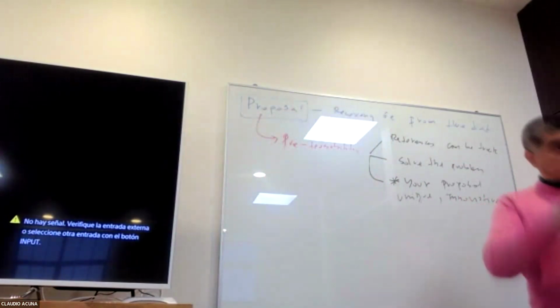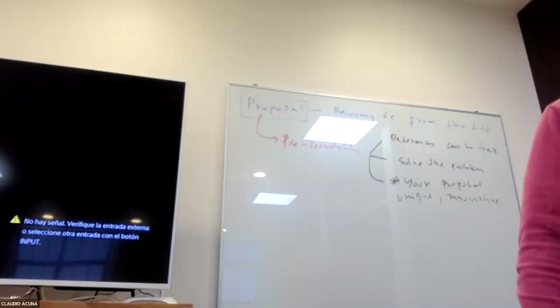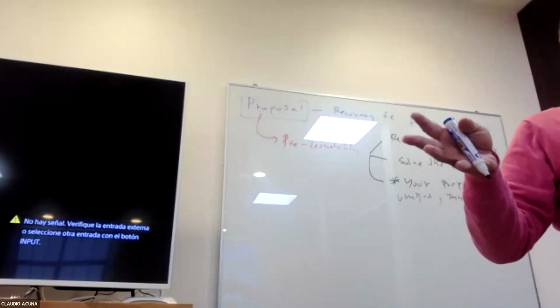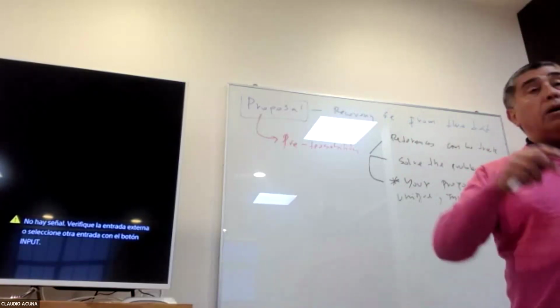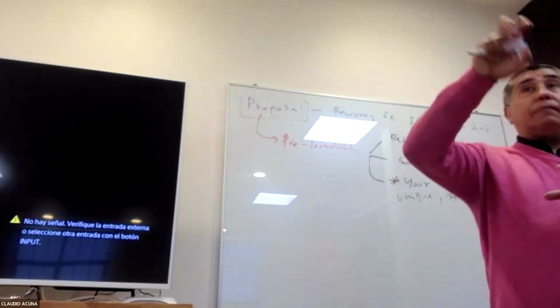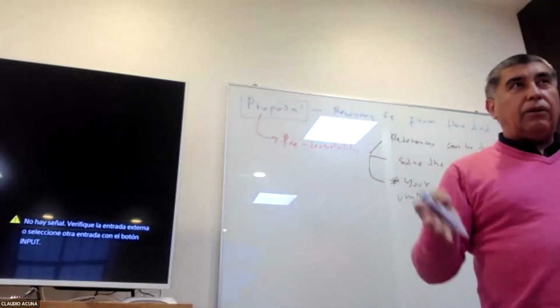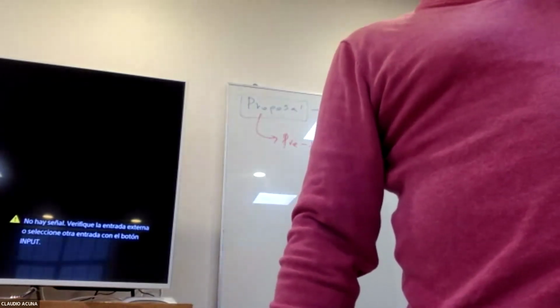The steps are characterization. What are the real steps to do this project at readiness level 4? Readiness level 4 means it can be bench scale but using real material. What are the stages that we need? First, characterize. That means X-ray diffraction to know the mineral types, or QEMSCAN to know the minerals, then chemical assay to know the elements, and particle size distribution. Analyze the variance between different samples, because you have variability with different samples. That will be enough as an experiment because we will charge for that.